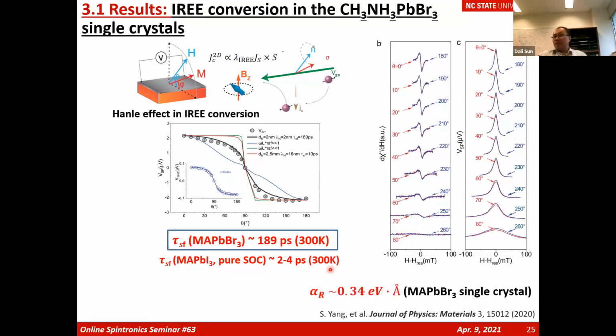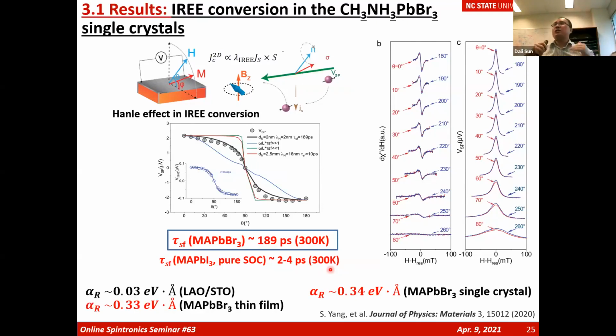So then we are able to estimate the Rashba parameter, which is still 0.3 eV·Å even in a single crystal, which is consistent with our thin film. It's orders of magnitude smaller than the ARPES result. So until now, it seems that our results confirm a negligible, or at least smaller, Rashba effect in such cubic structures, so that we are standing on the negative side, right?